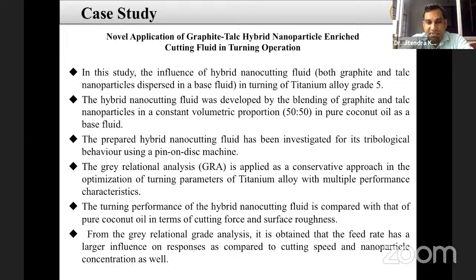This edible oil is unsaturated and biodegradable, and graphite and talc are also biodegradable. In that way, we can make a sustainable cutting fluid which can easily degrade, and we can use the minimum quantity lubrication method to increase lubrication and the life of the tool. We can also predict which parameters affect the responses more, which are surface roughness and forces.